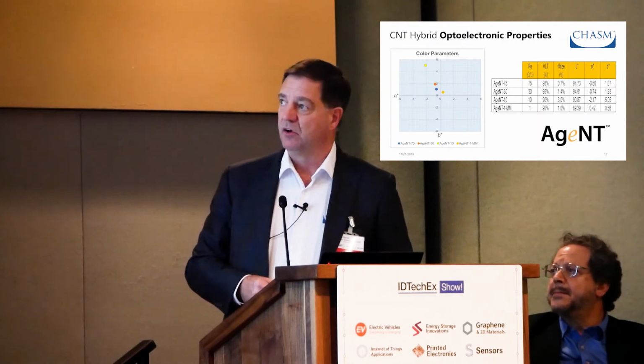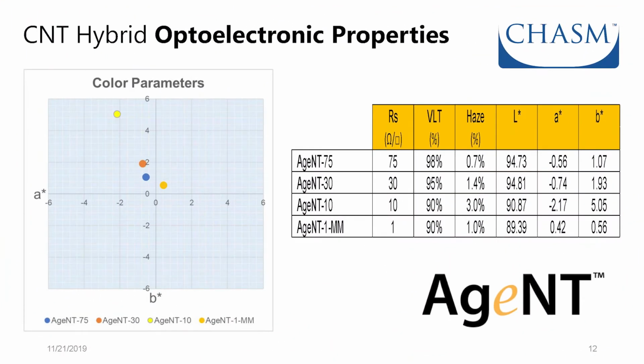Here is an overall summary of our product portfolio. You can see the different 75, 30, 10, and 1 ohm per square. The transparencies range from 90% up to 98%. The haze values that we achieve are respectable, not versus the optimized silver nanowire films like from C3 Nano, not as low in haze as their products, but we're really not aiming at the same touchscreen applications that they are.